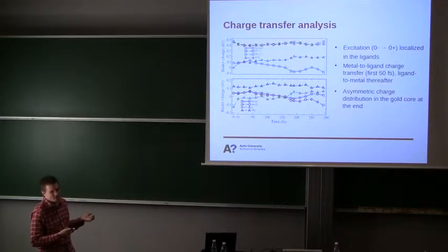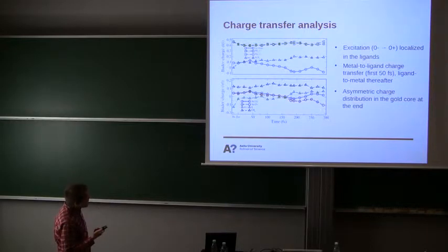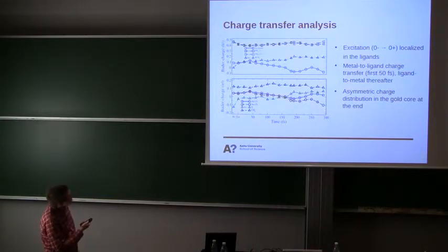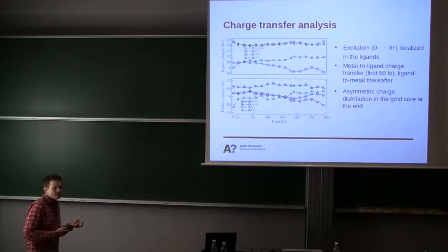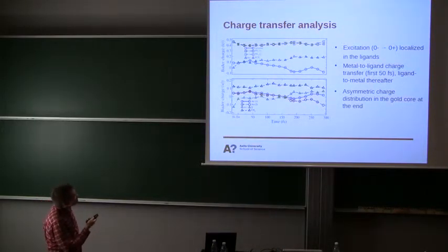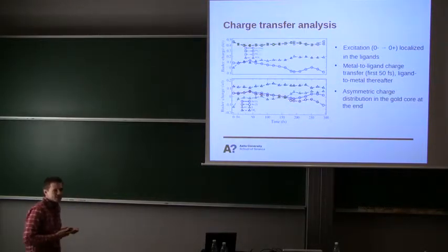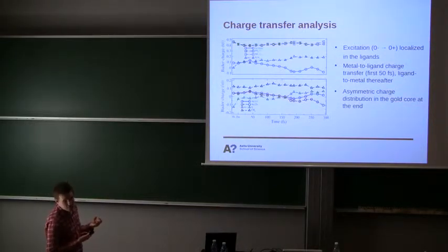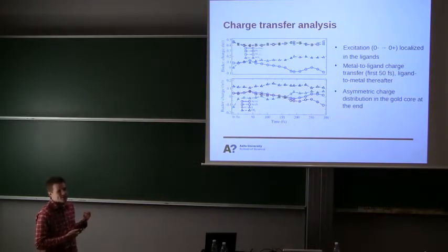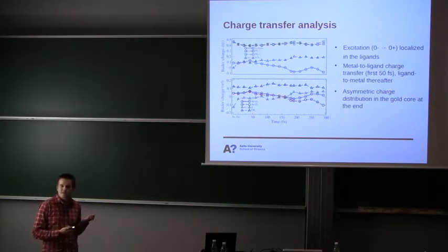So we also wanted to know something about the charge transfer. This slide is about that. Let's start with the fact that 0 minus here corresponds to the ground state, and 0 plus to the excited state in the beginning. Then we calculate the Bader charges and the whole electron density for different groups. The top figure is shown for the gold dimer, phosphine groups, and the SCH3 group, and the bottom figure for the two different gold atoms. The most interesting trend to be seen here is first metal to ligand charge transfer during the first 50 femtoseconds,